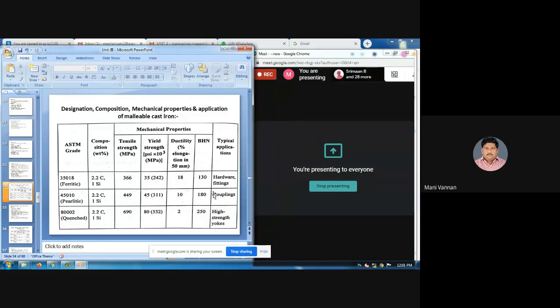Yield strength in PSI: 35 for ferritic, 45 for pearlitic, and 80 for quenched. Ductility, the percentage elongation: 18 for ferritic, 10 for pearlitic, then 2 for quenched. Then the Brinell hardness number of malleable cast iron is 130 for ferritic, then 180 for pearlitic, then 250 for quenched. Typical application of malleable cast iron.